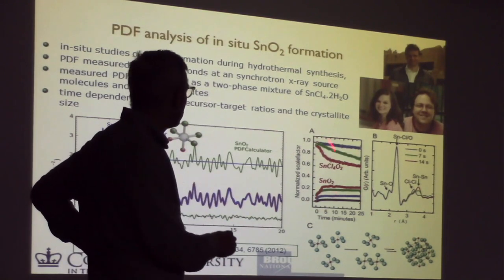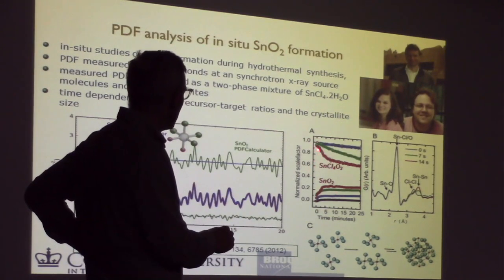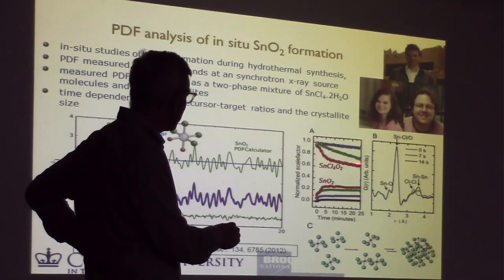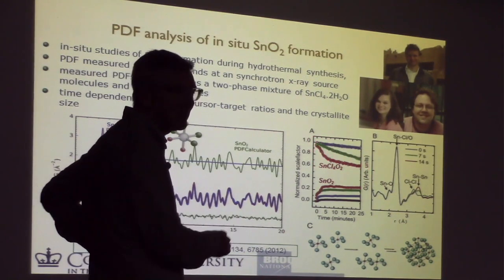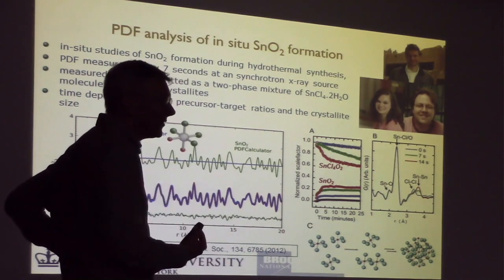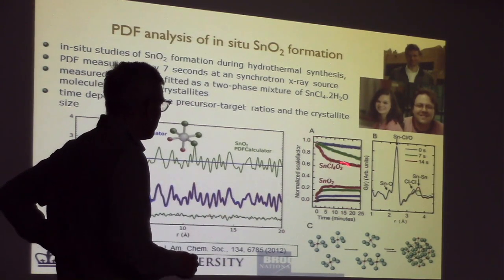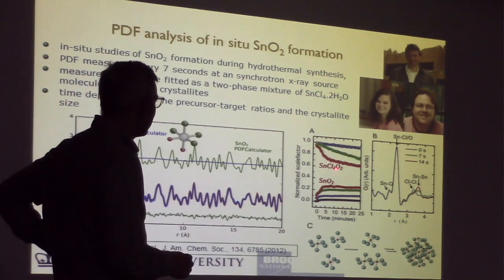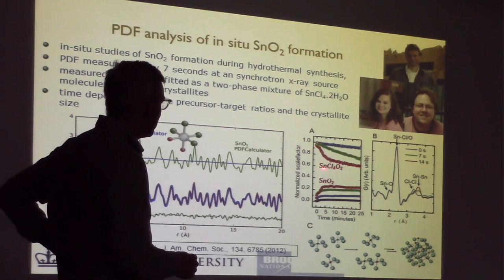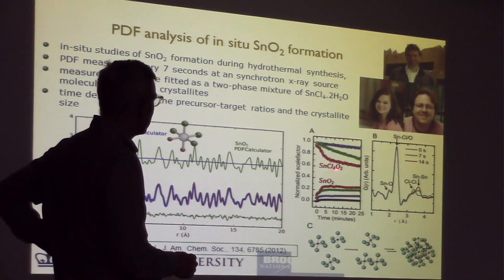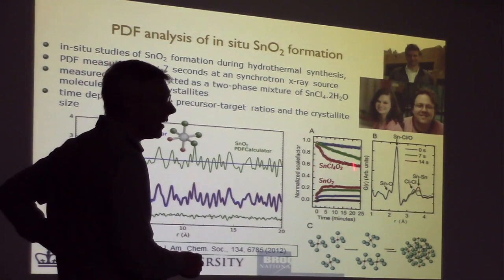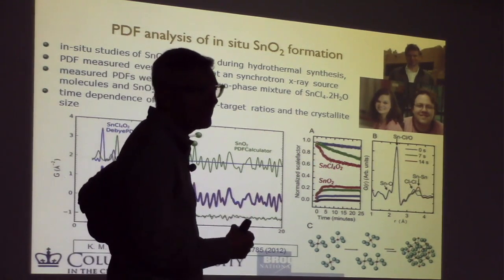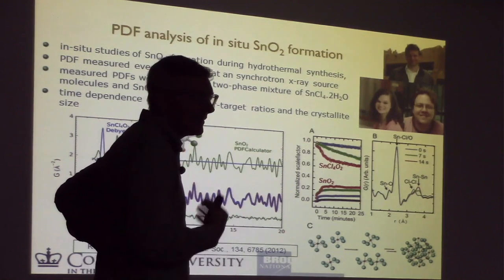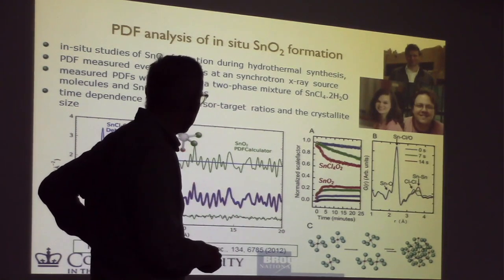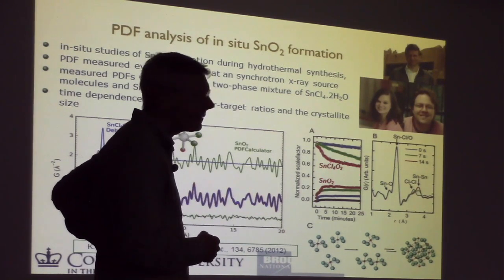And what was rather surprising was that only, say, 40% of the reagent was used up. Most of the reagent wasn't used. And the reason for that, again coming back to this thing, is that it turned out there are different forms of this cluster in there with different numbers of chlorines, and only one form of it was actually involved in the reaction and the rest was not. So you can learn from that: if you can make all of your reagent be this form, then you can get much higher yield.